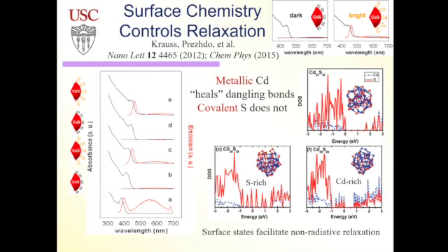And so what he does, he mixes two chemicals. One has cadmium, one has sulfur. And then he stops the growth. He heats it up, the crystal grows, and then he cools it down, it stops. And then he measures the spectra. So the first thing he measures, interestingly, is that you have this new line. So you have the first peak, the main peak that follows from particle in the box, but he has a very big feature that does not follow from the simple model. And this is from some trap states, mid-gap trap states.